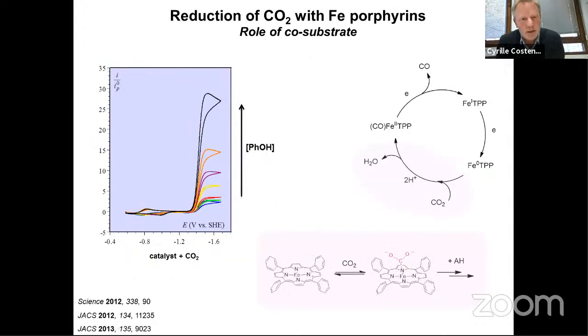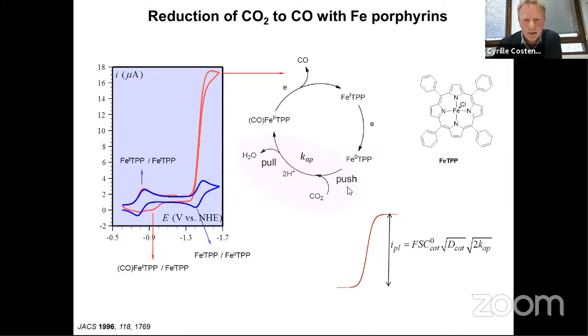What is interesting is that if you change the concentration of a co-substrate, as you can see, you need protons to release water, and the co-substrate here is a weak acid in DMF, phenol, for example. As you can see, as you increase the concentration of phenol, you increase the catalytic process and the plateau current. Here you have to increase the scan rate to really reach the plateau, but it's possible. And because, as I've shown here, the plateau current depends on the apparent rate constant here, it's possible to extract